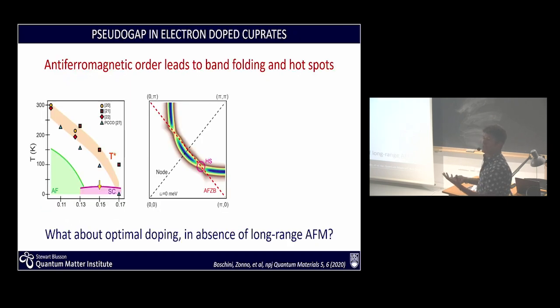Let me now move to another case, which is still cuprates, but now the pseudo-gap phase. And I'll do that on electron-doped cuprates. So this is neodymium cerium copper oxide. The difference from the hole-doped is that you have a very strong antiferromagnetic phase on one side, then you have superconductivity. And the question is, even here at optimal doping, we still have a pseudo-gap. You can see it if you look at the Fermi surface. Instead of a continuous spectral weight along the Fermi surface, you have a suppression of spectral weight where the Fermi surface crosses the antiferromagnetic zone boundary.